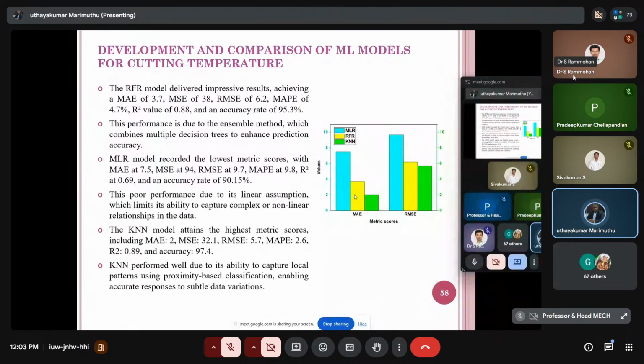So for the development and comparison of ML models for cutting temperature, you can see MAE, RMSE. The RFR model delivers impressive results, achieving an MAE of 3.7, MSE of 38, and so on. You can see these are the abbreviated values given, R square value of 0.88 and so on. This performance is due to the ensemble method, which combines multiple decision trees to enhance prediction accuracy. The MLR model recorded the lowest metric scores with the MAE at 7.5, MSE at 94, RMSE at 9.7, and so on.